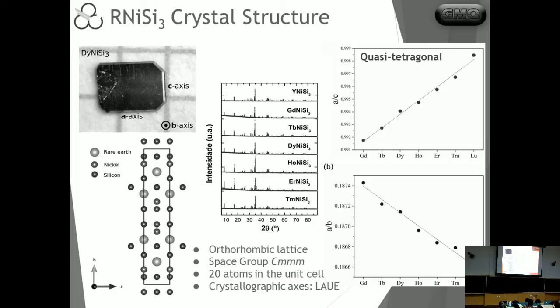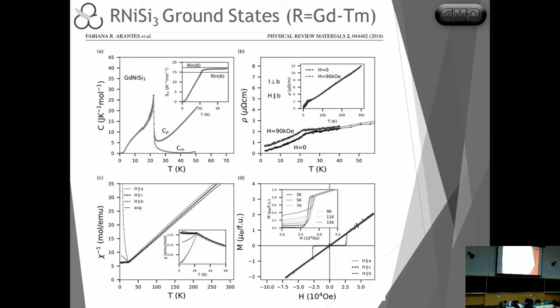And at the same time, we can see that the B-axis starts straightening out. So as it goes from orthorhombic to tetragonal, the lattice also stretches in this direction up here. We could also then orient the crystals and do the orientation dependence characterizations there.